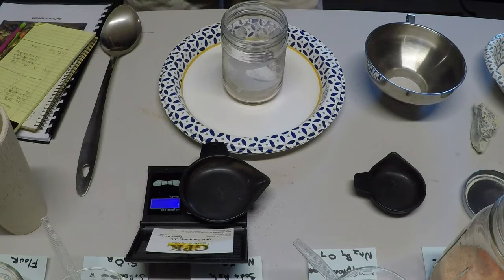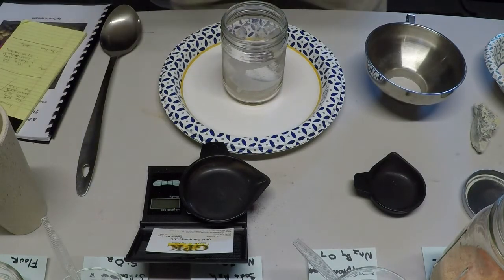Now, we have 140 grams of lead in there. But we don't want a 140-gram lead prill. We only want about a 30-grammer. So we add a reducing agent. A reducing agent that we're going to add at this point will be flour. What happens in that crucible fusion is you add a given amount of a carbon source to the crucible fusion, and flour, or whatever your carbon source is, tries to burn inside of that oxygen-free environment inside of the crucible. The only way it can burn is to steal oxygen atoms from something that's in there. And basically what it will do is steal oxygen atoms away from the lead oxide. When the oxygen atoms are removed from the lead oxide, it becomes metallic lead.